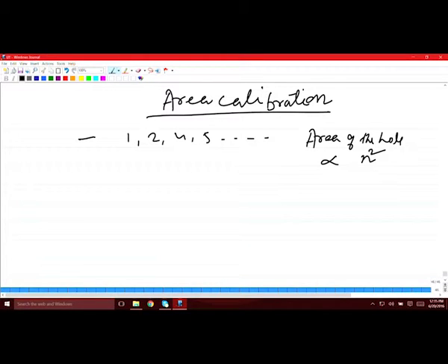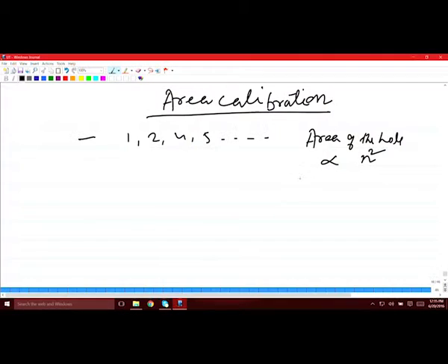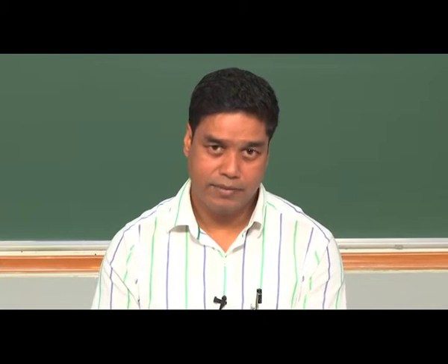So, for example, if you have selected a number 5 hole, then the relative area will be 25. So, this is how you can collect the signal intensities from this hole as a function of the area by simply providing the square of this number as the area.